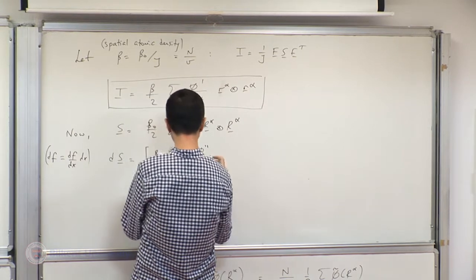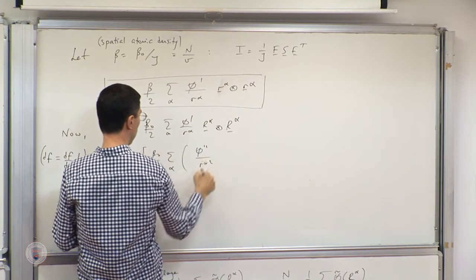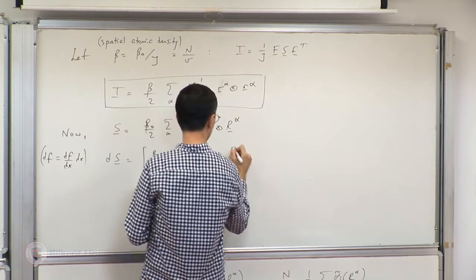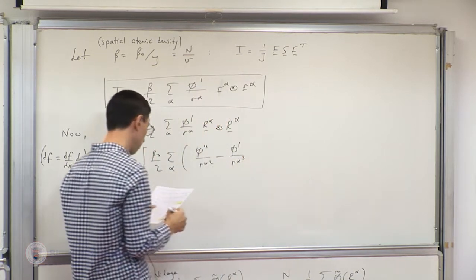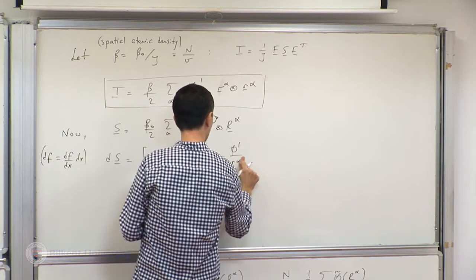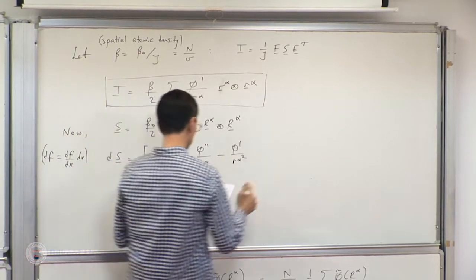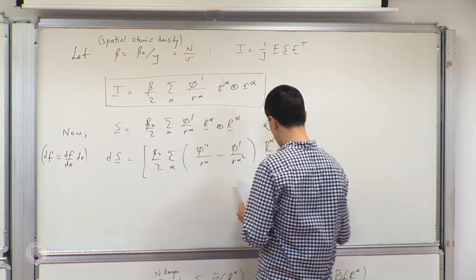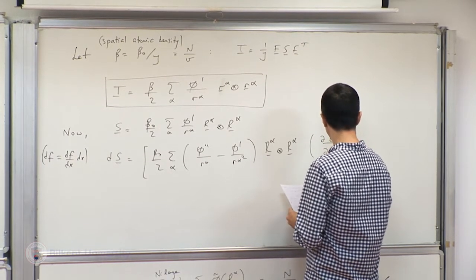From the previous board, the derivative of r_alpha with respect to F was found to equal 1/r_alpha times the vector r_alpha tensor-producted with the capital R_alpha operating on dF. What I now see is a second-order tensor, then a scalar product, then another second-order tensor. I combine these into a fourth-order tensor operating on a second-order tensor.